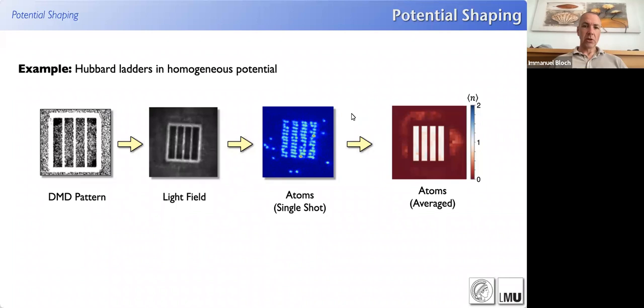So this is actually a single snapshot fluorescence image, as the one I showed you before, of atoms loaded into the lattice plus this structuring light field potential. And you can see indeed the atoms nicely occupy only those sites where we want them to be. You can then average this, for example, for thousands of shots, and you can then record the average density distribution telling you, for example, how homogeneous are my potentials, how are the atoms distributed in the system.